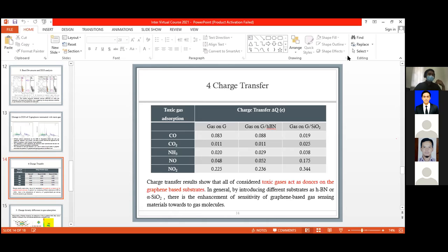I don't think so, because we have tested many different K-point samplings, and the calculation has been tested first for freestanding graphene, and we confirmed the result of the zero band gap of graphene. After that, we expanded to the effect from the substrate. The bands generated from the substrate modify the band, which contributes to the gap at the Dirac point.